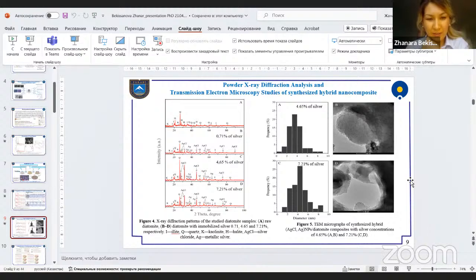Thanks for the question. We only characterized that. We can see, for example, in the peaks, when the concentration is increasing, the peak is higher than at the lower concentration. It is the formation of silver chloride and silver nanoparticles. And in this work, we did not artificially add silver chloride. It is from impurities. It is the first ion exchange reaction, and after that it is reduced with hydrogen peroxide.